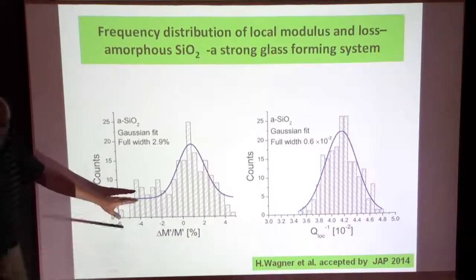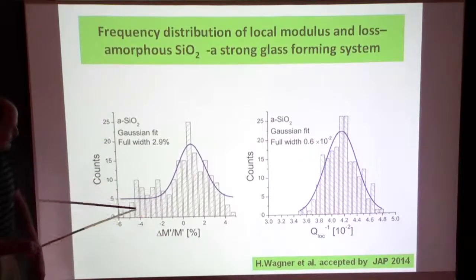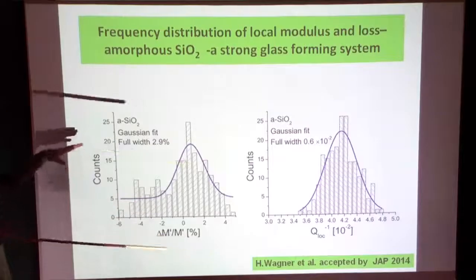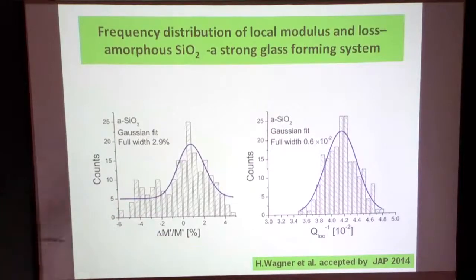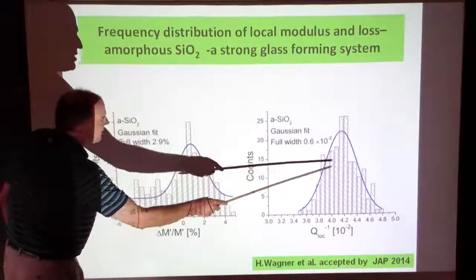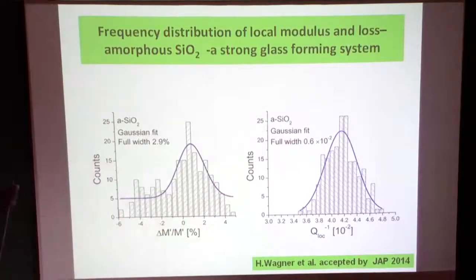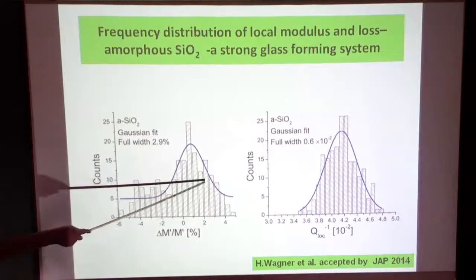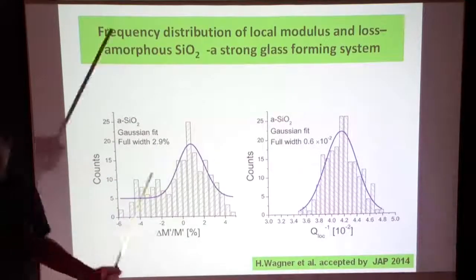Those of you who are interested in that, you see that there is always some kind of long-range flanks over there, which is something peculiar to us. And also the losses are much smaller in the width, so the distribution is much smaller. Kramers-Kronig relation must hold anyway, so that's okay. But again, this is a factor of 10 smaller than for the fragile metallic glass.